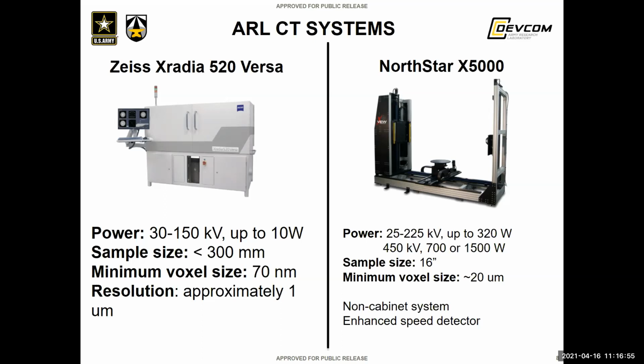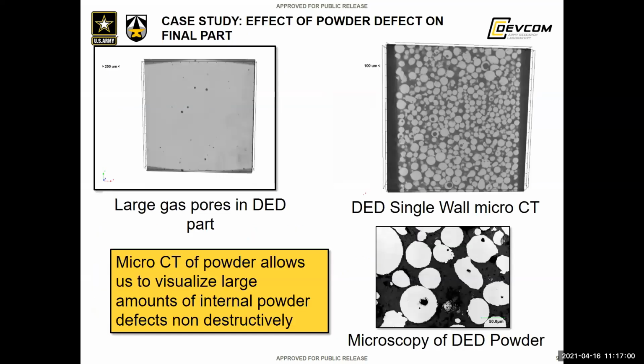Getting into CT and the benefits, here is a case study. As we were transitioning a high strength steel from powder bed fusion, like the 320, to a DED, we noticed while doing our non-destructive evaluation that there are large gas pores in this DED part. As you can see here, these very large circles are usually entrapped gas, and historically speaking, that entrapped gas is from the powder itself.